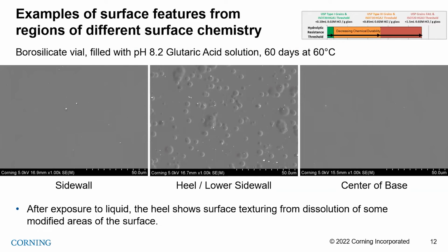And that's visible in terms of surface roughness. So again, with an electron microscope, we can see pitting and features. Now, those features aren't a representation of the bulk glass chemistry. Those are an artifact of this forming process. And so those are only hundreds of nanometers or microns deep, and a result of this evaporation and condensation process.